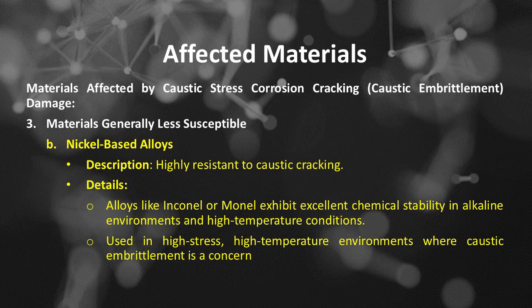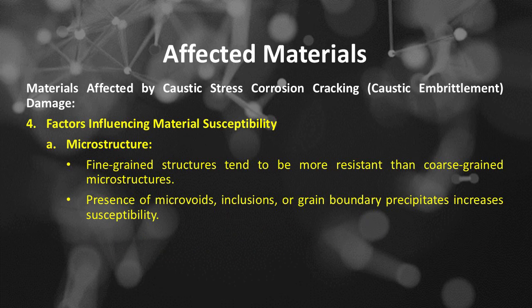Number B, nickel-based alloys. Highly resistant to caustic cracking. Details of nickel-based alloys. Material affected by CSCC. Alloys like Inconel or Monel exhibit excellent chemical stability in alkaline environments and high-temperature conditions, and are used in high-stress, high-temperature environments where caustic embrittlement is a concern. Number 4 of materials affected by caustic stress corrosion cracking or caustic embrittlement damage is factors influencing material susceptibility.